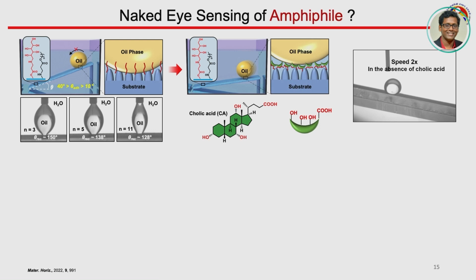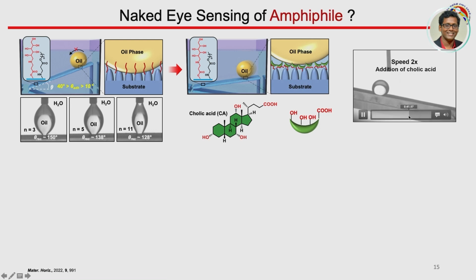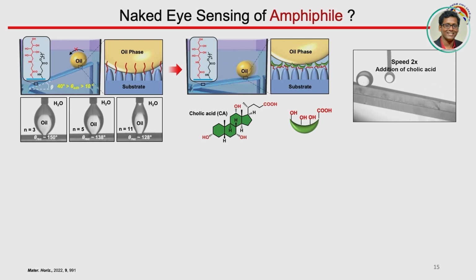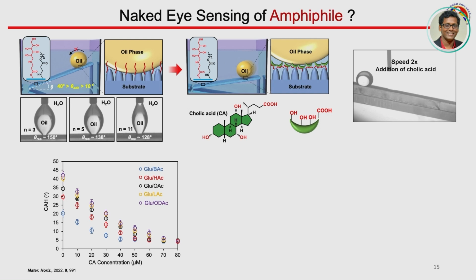If you see these particular demonstrations, initially it was adhesive, you put the oil droplet, nothing is happening, then you add the cholic acid. Once the cholic acid is placed, then on the next place of the same coating, put another droplet, just to make it a little faster. You will see that once he places this oil droplet, it immediately rolls off. So on the same surface, you are precisely performing this chemistry on top of the surface, and that allows you to sense this cholic acid, one of the bile acids, across this entire range.